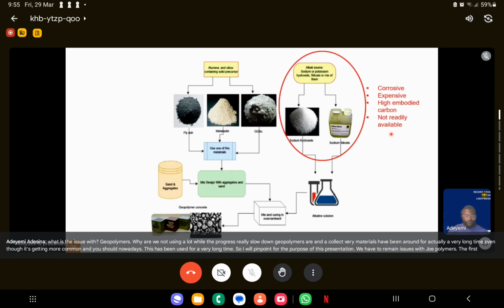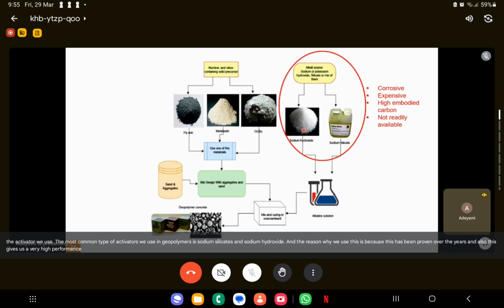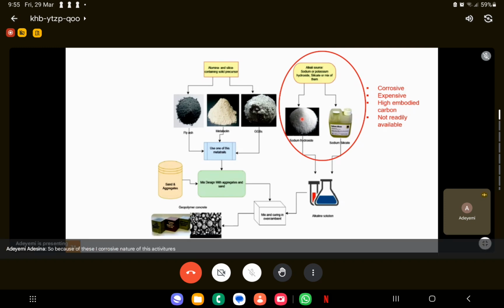The first is the activator we use. The most common activators in geopolymers are sodium silicate and sodium hydroxide. The reason we use these is that they have been proven over the years, and they give us very high performance compared to alternatives. But the problem with this conventional activator is that, first, it's very corrosive. Sometimes we use sodium hydroxide up to 4 molar concentration. That is a lot. That will burn the skin. Because of the highly corrosive nature of these activators, it is not practical to use on a large scale. In fact, in some cases we can't use traditional concrete mixers to mix this kind of geopolymer.